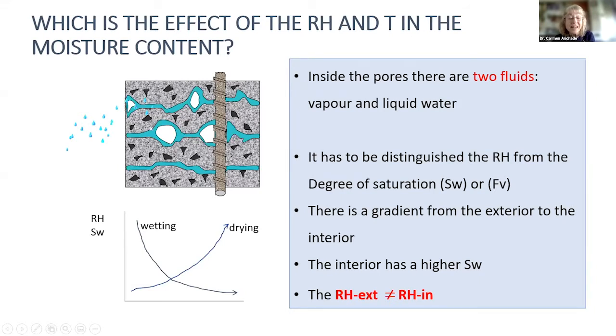If this rain is evaporated before it has the time to reach the bar, a short rain is not influencing the corrosion of the bar at all, because there is this gradient, and drying is longer and wetting is quicker because of the capillarity. But here is the summary.